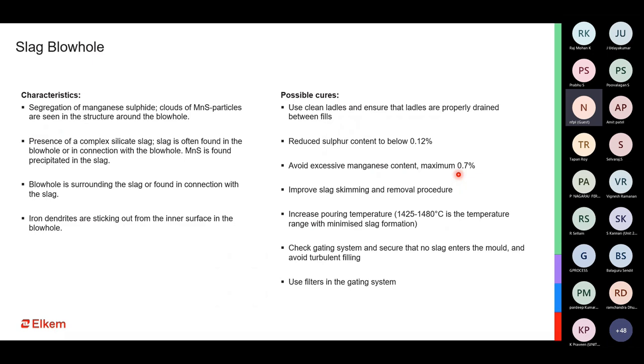Use of filters is definitely one of the solutions to resolve or control slag inclusion into the casting. But sometimes filters are not sufficient because the slag can be a bit viscous and liquid slag in the beginning, and thereby it does have the tendency to pass through the filters. So just having the filters alone may not always give you a 100% solution to the problem. We'll have to also make sure that our systems are taken care of before it goes into the gating system.